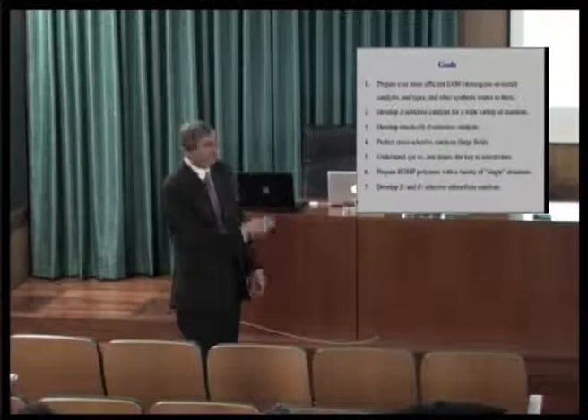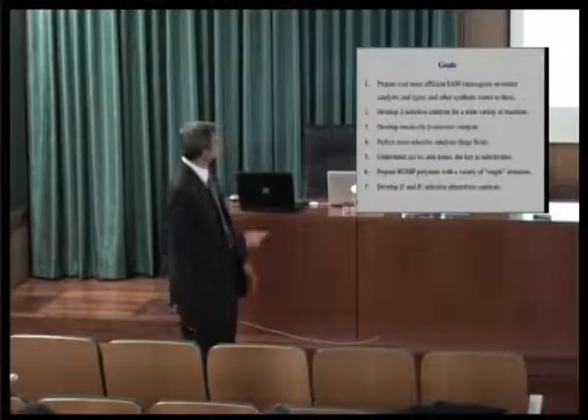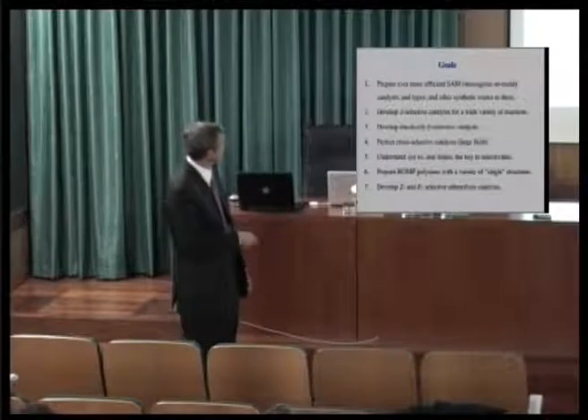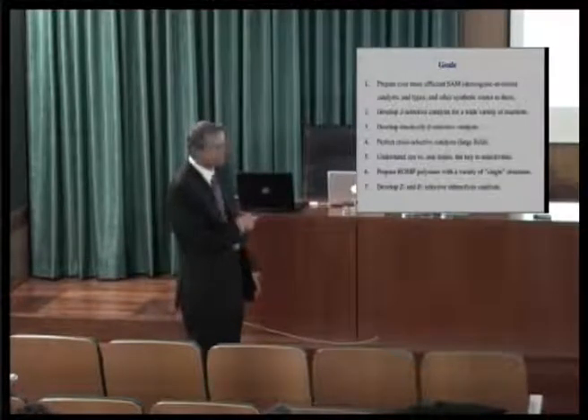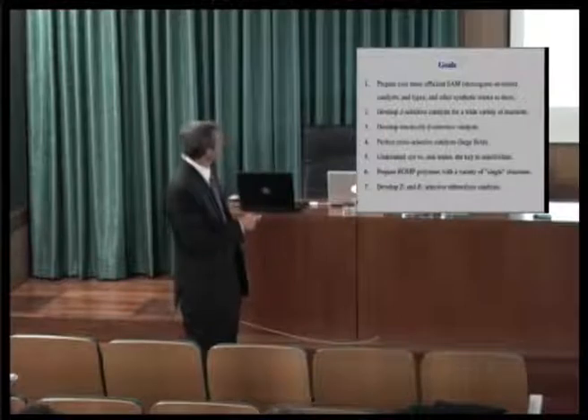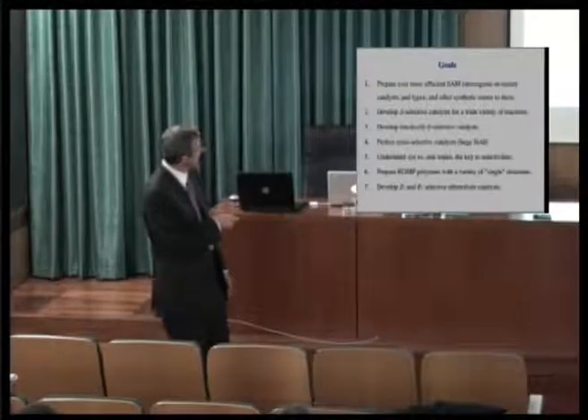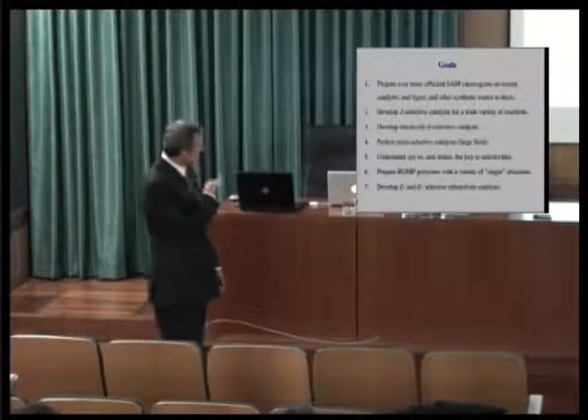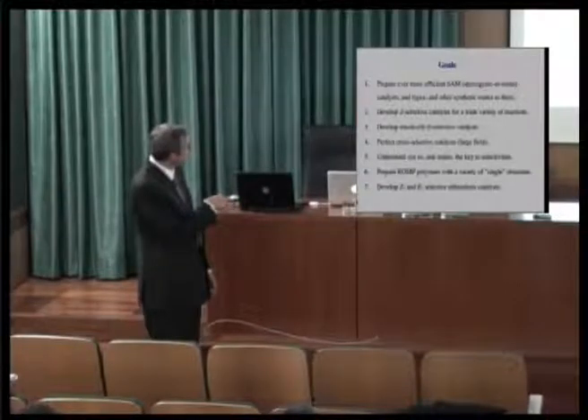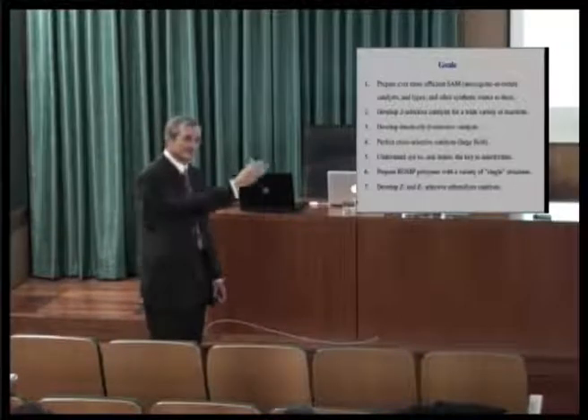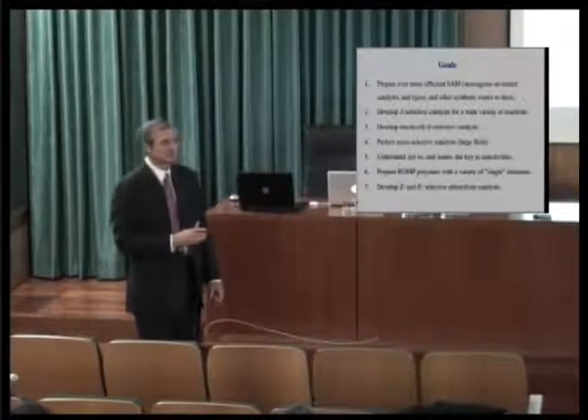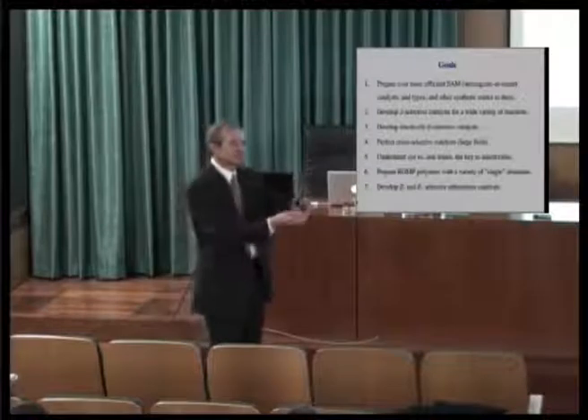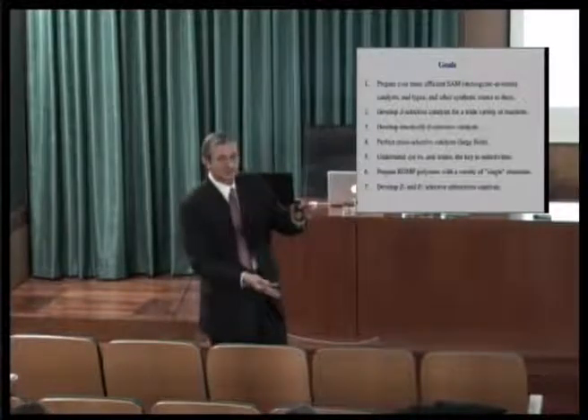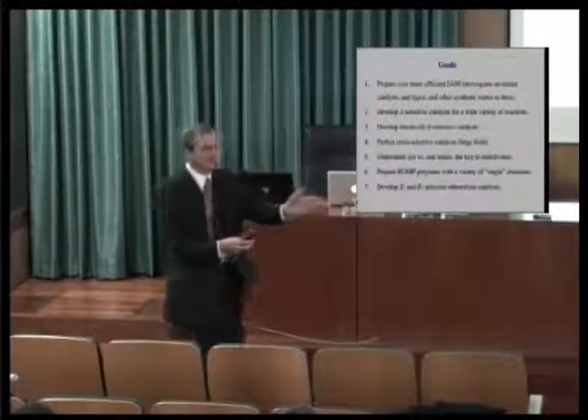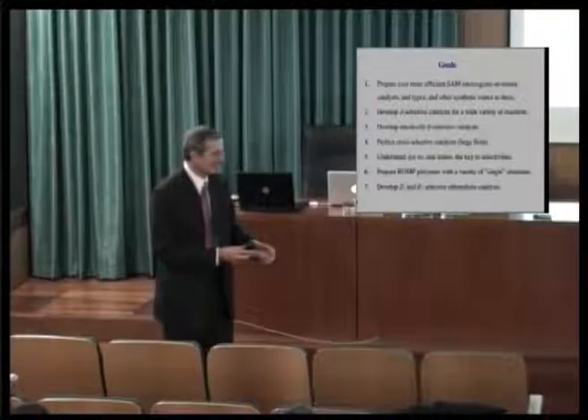So we have a lot of goals. More efficient catalysts, obviously, Z selective catalysts. Kinetically E selective catalyst would be very nice. We have a lot of things to understand. We have a lot of polymers to make. And we are showing that, in fact, you can run ethenolysis reactions that are also Z selective, which is a very good way to take a mixture containing 25% Z and 75% E and eliminating the Z component through an ethenolysis reaction.